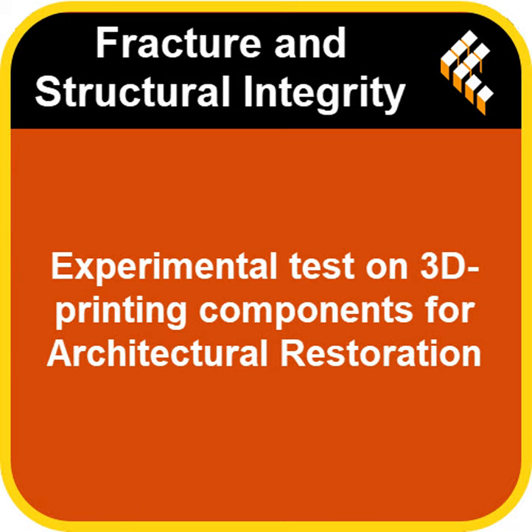Okay. From pulling those dog bones, they got the core numbers for their printed PLA. Average stiffness, the Young's modulus, was about 1,270 MPa. Average tensile strength, 44 MPa. What do those numbers mean practically? Is 44 MPa good? Well, MPa is megapascals, a measure of pressure or stress, force per area. 44 MPa tensile strength is actually quite respectable for standard 3D printed PLA. It's not steel, obviously, but it's strong for a common plastic. And the 1,270 MPa stiffness? That tells you it's reasonably rigid. It won't stretch like rubber. It holds its shape pretty well under load. And importantly, these results were very consistent.